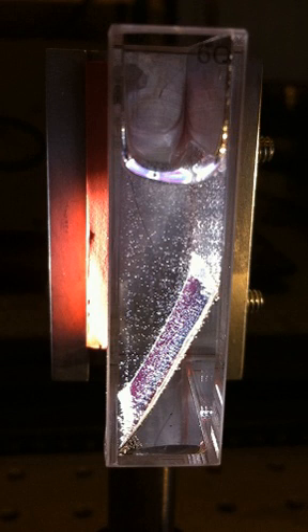Visible light water splitting with a one-piece multijunction semiconductor cell, versus UV light with titanium dioxide semiconductors, was first demonstrated and patented by William Ayers at Energy Conversion Devices during 1983. This group demonstrated water photolysis into hydrogen and oxygen, now referred to as an artificial leaf or wireless solar water splitting, with a low-cost, thin-film amorphous silicon multijunction cell immersed directly in water. Hydrogen evolved on the front amorphous silicon surface decorated with various catalysts, while oxygen evolved from the back metal substrate, which also eliminated the hazard of mixed hydrogen-oxygen gas evolution.